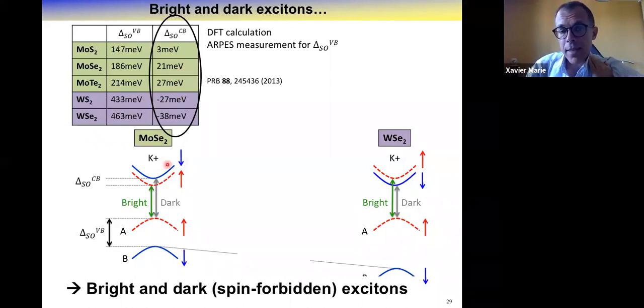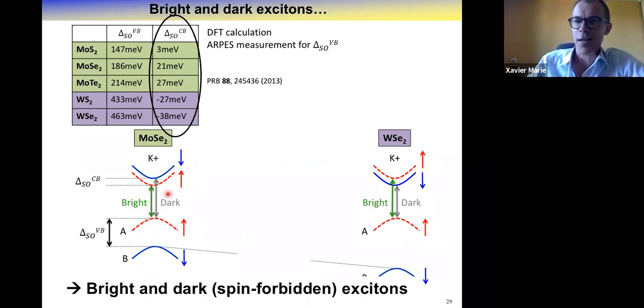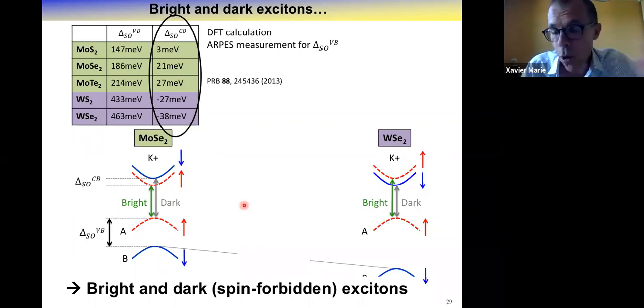Now when you form your exciton, you have two possibilities. Either the exciton is formed with conduction and valence states with the same spin, up in red here, or with opposite spin, down and up. It can be shown that if you have the same spin, this exciton from a symmetry point of view can couple to light. It's a bright exciton. Whereas if you have opposite spin, in principle, and you will see why I say in principle, it is spin forbidden, it should be dark. No radiative recombination. So for instance, in WSe2, you see that the lowest energy transition you predict in this simple picture is a dark exciton, whereas the bright one is at slightly larger energy.